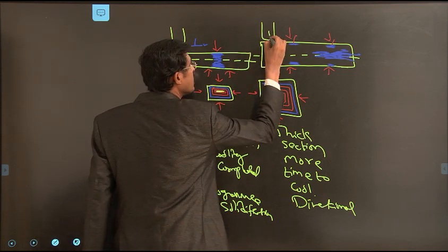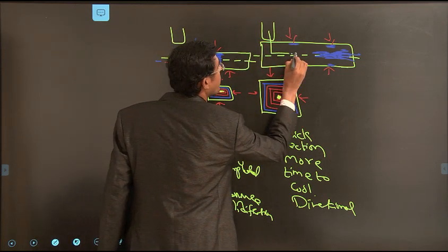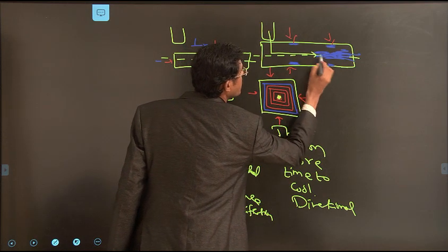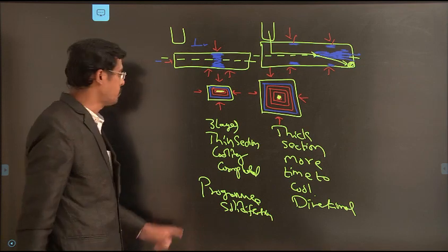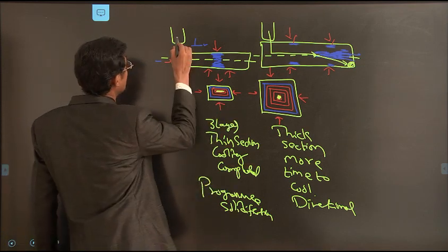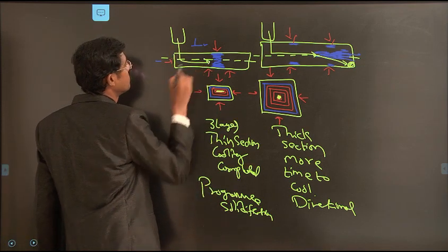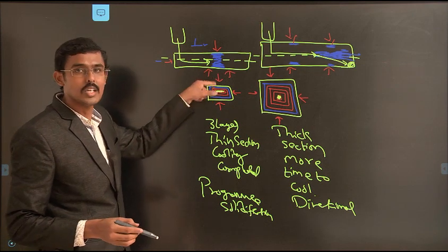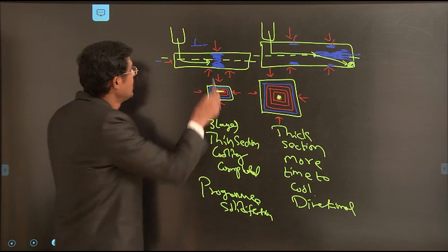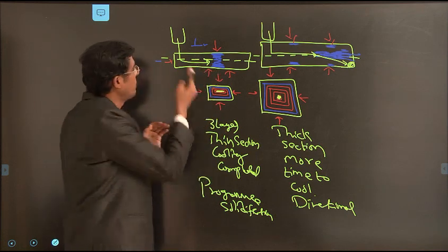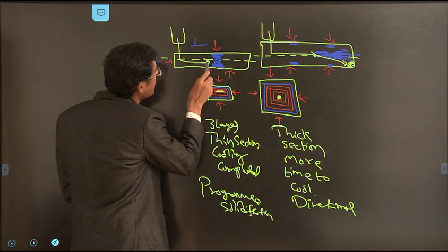this feeder of molten liquid should pass away to the entire location up to this corner to fill. In case of progressive solidification, this is not possible. It is stopped here because due to perpendicular progressive solidification process, the thin section is solidified quickly and blocks the region, not permitting it to go here.